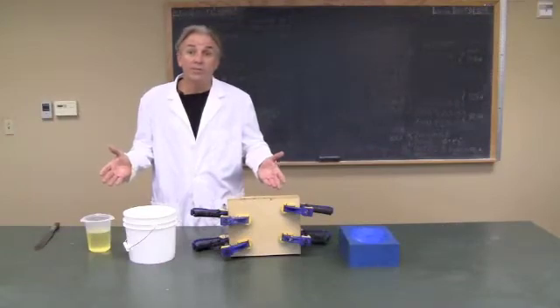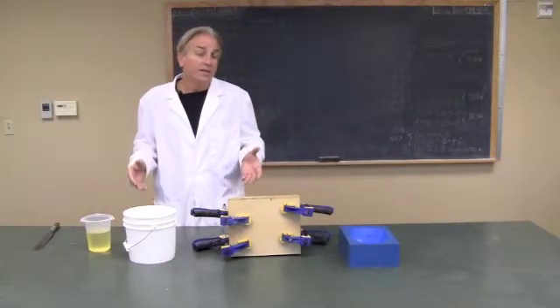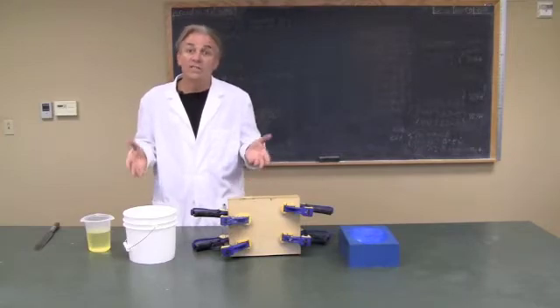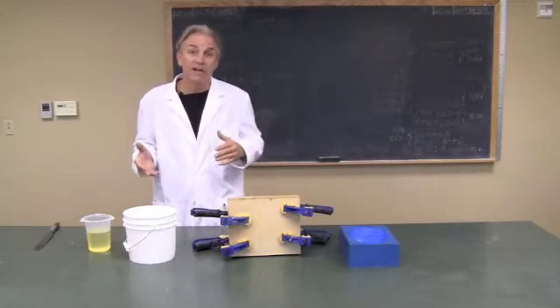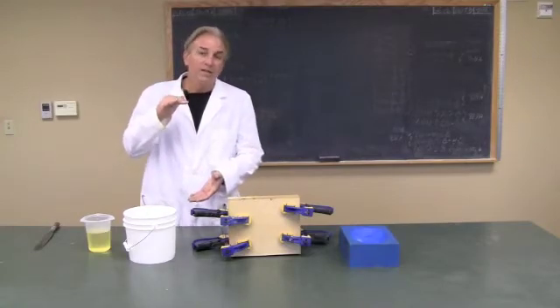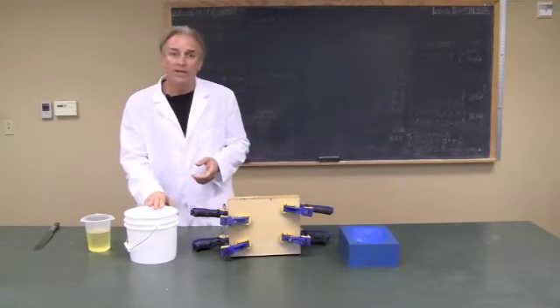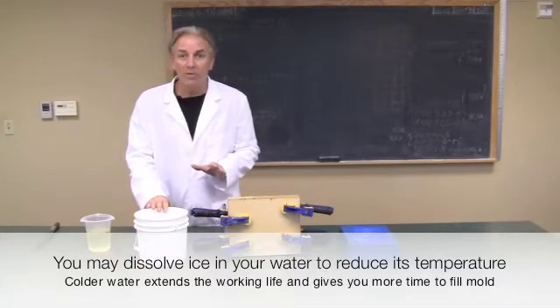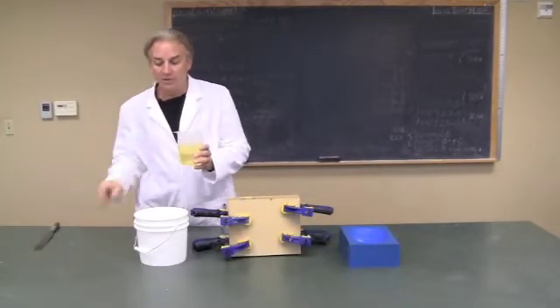Now we're going to demonstrate the product HydroSpan 400 to you. In this case, we've chosen to shrink the part to 30% or 70% less than the volume of the master. If it were like a nine inch tall image, it would shrink down to three inches tall. I've got my water ready—I want to use ice cold water to give me as much working time as possible. So I have four parts water here by weight, and I have my HydroSpan here that's already pre-measured.